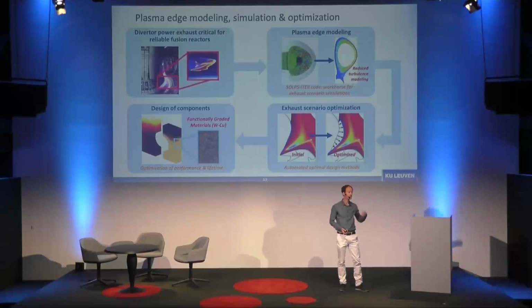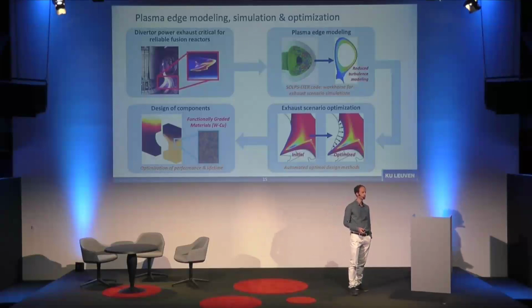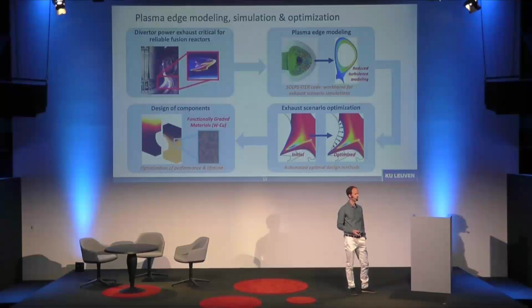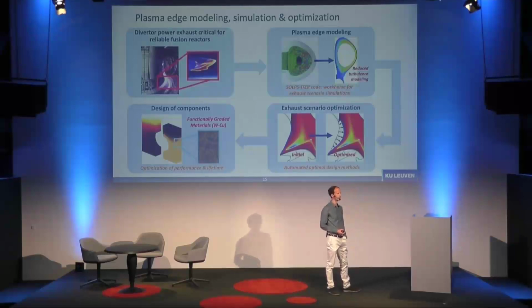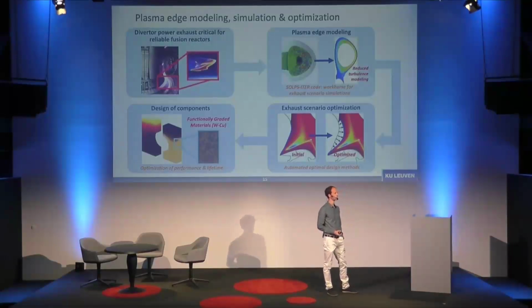Hi, very nice talk. As Jeff mentioned, we just had the DT campaign in JET, and one of the things that we really would like to find out, and where I have the impression you might be of big help, is because we have this tungsten divertor, we get high heat loads, we have sputtering of tungsten from there, and then that migrates towards the mid-plane, and because the plasma is rotating very rapidly, it tends to form a highly radiating blob, because tungsten radiates a lot because it has a high Z value. Would your codes be able to capture this kind of physics and get us an improved understanding?